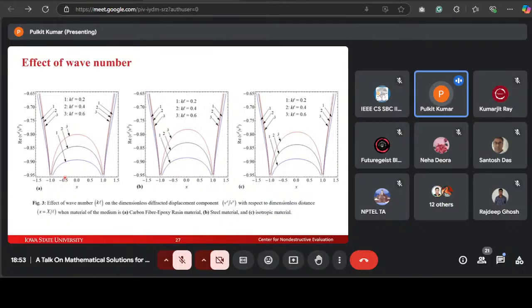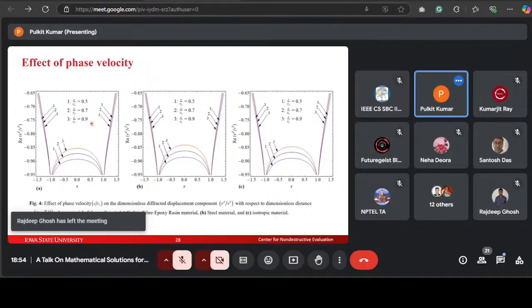So now the effect of the wave number. This figure shows the dimensionless wave number increases the diffracted displacement both inside and outside of the strip for all the considered materials. The effect is strongest and reaches the highest value when the infinite medium is steel. You can see here compared to these two materials. So this is the phase velocity. This figure shows the dimensionless phase velocity increases the diffracted displacement. When comparing figures A, B, and C, it is clear that the effect is stronger when the infinite medium is steel.